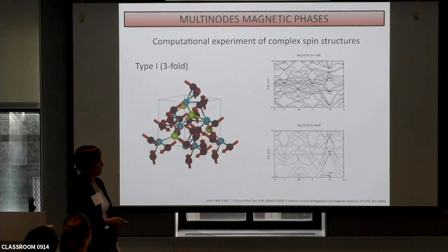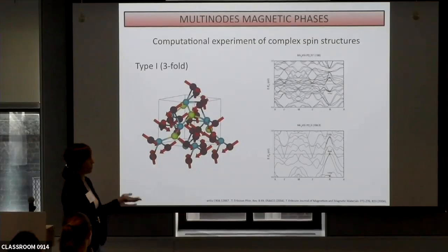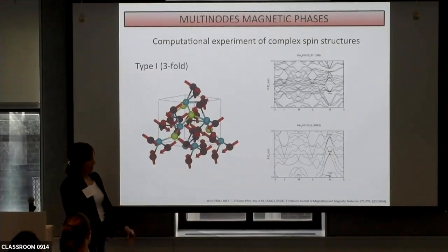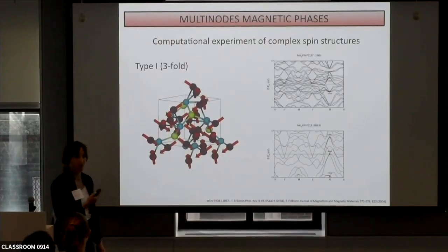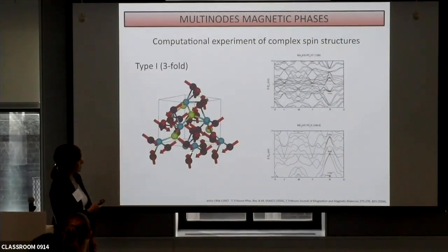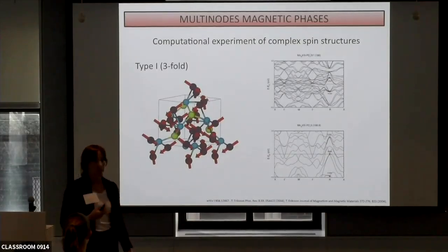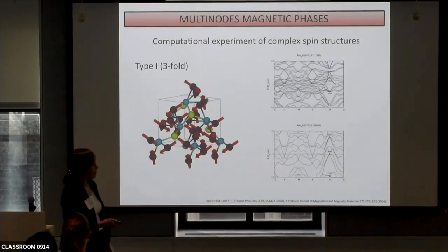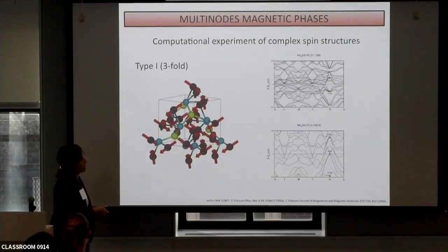We calculated the band structure for Hubbard U equals 3, and we found a 3-fold crossing at the Fermi level. This U equals 3 actually reproduced the magnetic moment that was measured. But is this actually true? Is there a 3-fold here? This is something we don't know, because when we have a chiral space group magnetized in an antiferromagnetic way, usually the strength that DFT provides is not enough. So we will only find out whether there is a 3-fold at this point or not with the experimental realization of the compound.